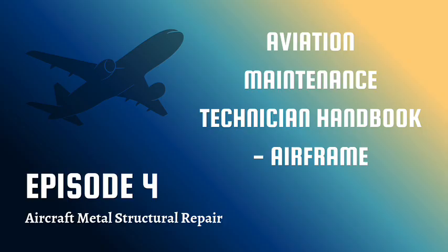Alloy matching seems key. It's the first rule. Whenever feasible, use rivets made of the same alloy as the parts you're joining. So if you're riveting 2024 T3 skin, ideally use 2024 rivets. If it's 1100 or 3003 material, use 1100 rivets. Why is that so important? Two main reasons: maintaining the design's structural strength and, crucially, preventing galvanic corrosion. Mixing dissimilar metals creates a battery, especially with moisture present, and the more active metal will corrode away. Sticking to the same alloy avoids that.